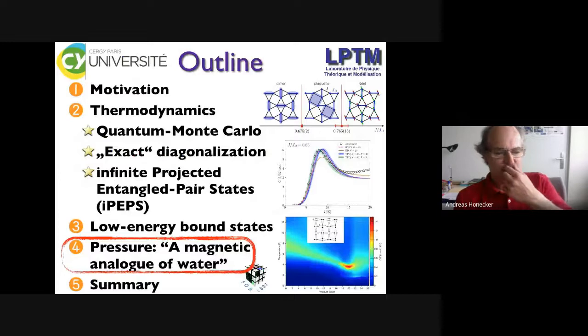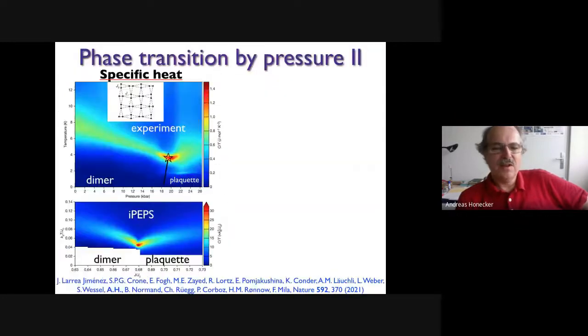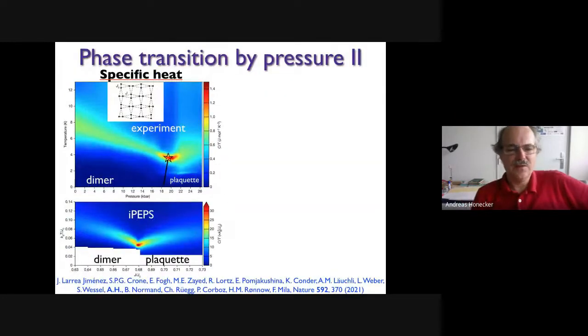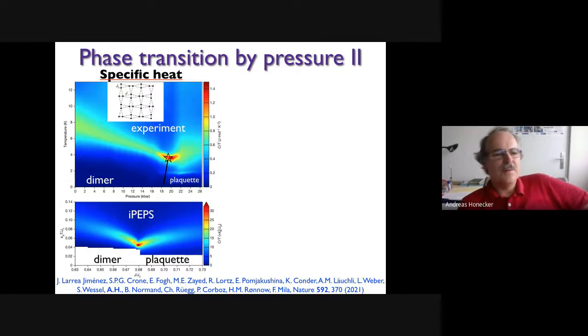Okay, so for the last 5 minutes or so, I want to quickly walk you through a recent experiment that was done after we had developed the methods. Here on the top left is an experimental result for the specific heat of strontium copper borate at low temperatures under pressure. What you see here is a maximum as a function of pressure that is actually developing into a peak, and a strong peak at a particular pressure.